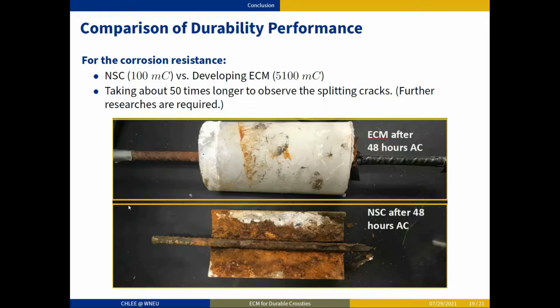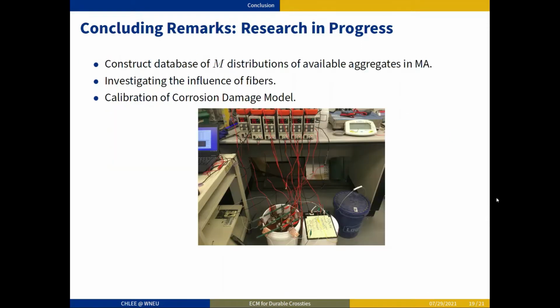So if you see the picture over here, after 48 hours of the accelerated corrosion test, ECM looks almost intact. As compared to that, normal strength concrete after 48 hours of accelerated corrosion has reinforcement that is significantly corroded, and it was broken. In summary, we will keep working on developing a better ECM for concrete crossties.